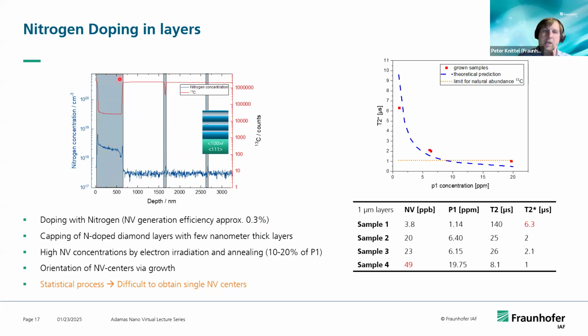This is a SIMS profile that shows first the nitrogen in blue that is incorporated, and in red you see actually the 13C concentration. This is an advantage that you have if you're doing growth. You can also control the amount of nuclear spins by using a methane that is isotopically enriched, but I will come a bit later onto that. Again, the concentration of your P1 center determines the characteristics of your diamond. If coherence times, like here the effective spin dephasing which is here 6.3 microseconds, are below the theoretical prediction, you probably have incorporated additional spin defects in your crystal.